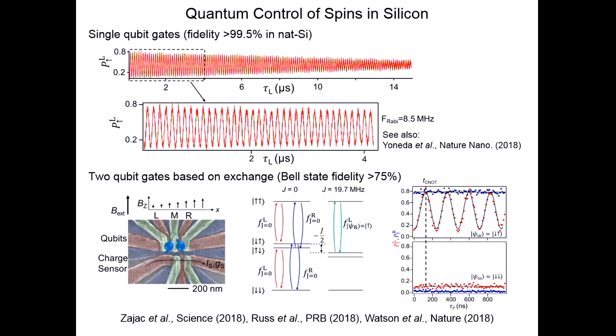It's not even the isotopically enriched silicon. See Rabi oscillations that persist out to tens of microseconds. And we've done very careful measurements. It's called randomized benchmarking to determine the fidelity of these gate operations. And you can see in the first experiments with these devices, better than 99%.